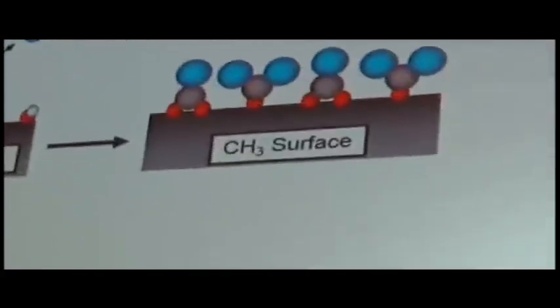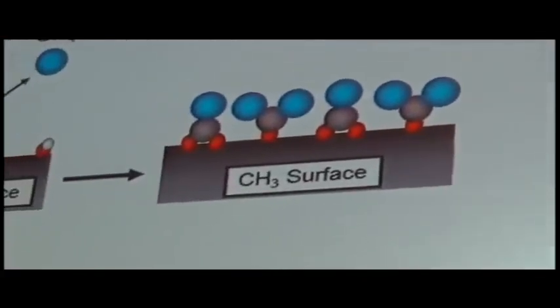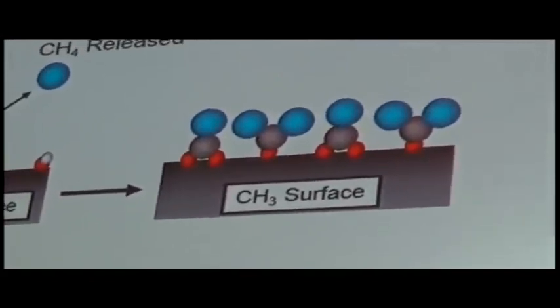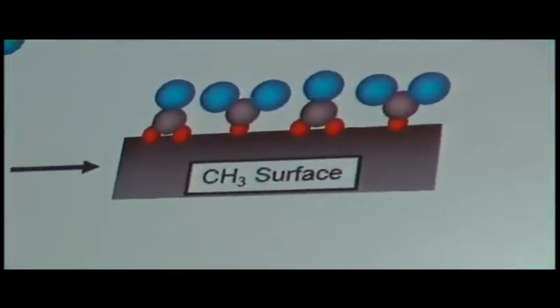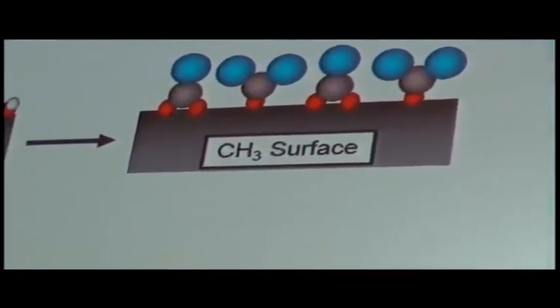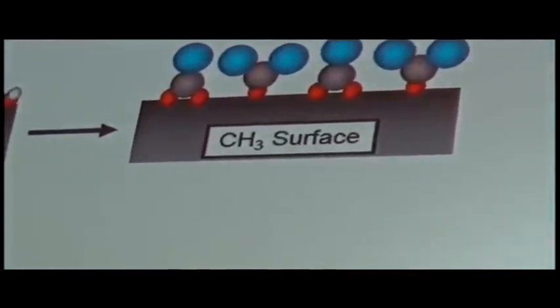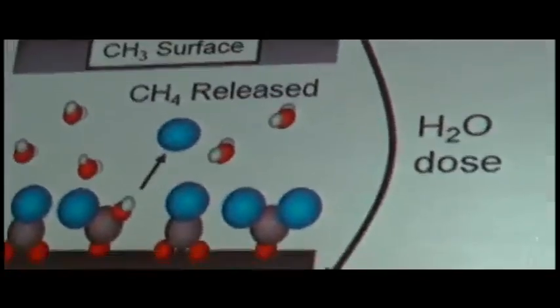Eventually, we're going to do one of two things. We're either going to saturate the material, which most of the cartoons you see for this show. We find, for the most part, we don't get that, because the ligands that are left over are taking up so much space, we don't completely saturate. So no matter how much of the metal alkyl we add, we end up with still only less than a monolayer of the material going on. After that, we stop feeding in the alkyl group and start doing a decomposition step.